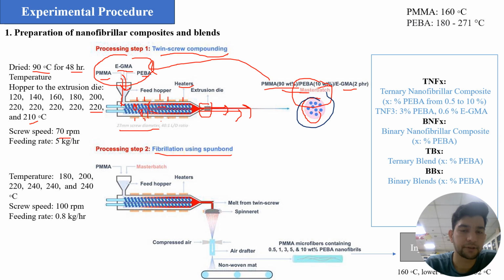To obtain the master batch, first we dry at 90 degrees centigrade for 48 hours, and also PMMA. Then the same process here: we add to the feeding hopper, and the temperature ranges from 180 to 240 degrees centigrade. The screw speed is 100 RPM for this mixing and the feeding rate is 0.8. Okay. So after melting and mixing, the polymer blend will go out.